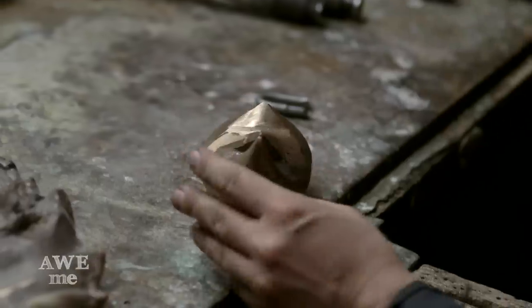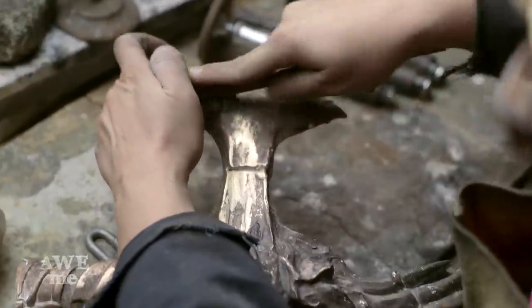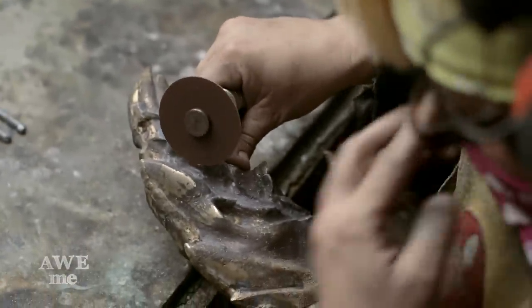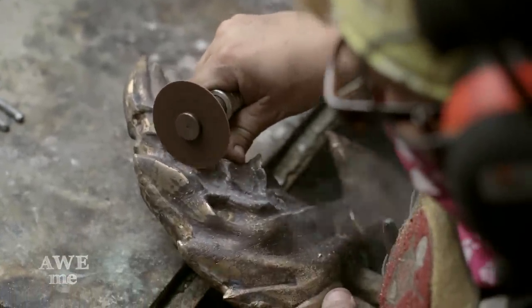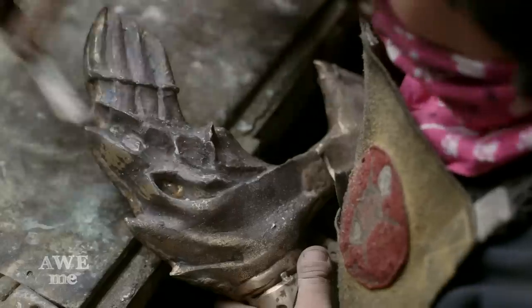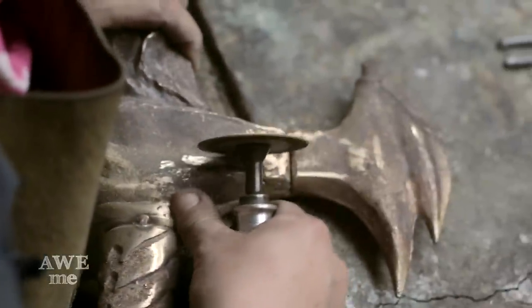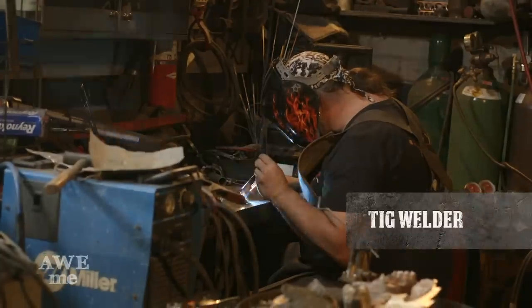Hilt, grip, and pommel were cast solid in bronze after we pulled that out in pieces from the lost wax investment casting for the bronze pour. They were way too heavy. It probably weighed 50 or 60 pounds. So we took those to the bandsaw, cut them in half, and then took them to the mill off camera and milled out the interior to make them hollow, and then TIG welded everything back together.